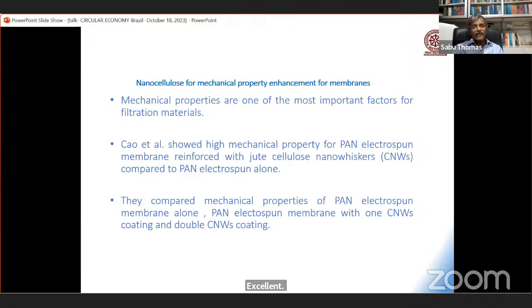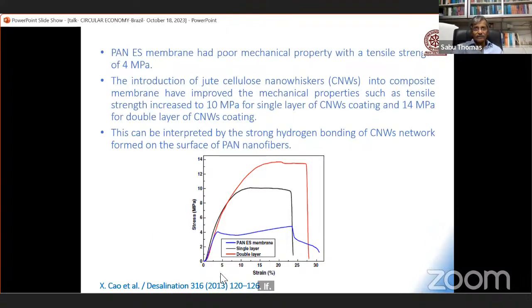I want to tell you that nanocellulose is an excellent reinforcement because you give nanocellulose coating on electrospun fibers. You can see this is the PAN membrane. The PAN is interesting for mechanics, but the mechanical properties are very small. You give a coating, one-side coating, see on PAN, you see the line goes up. You give one more coating, you see a high increase in the mechanical properties.